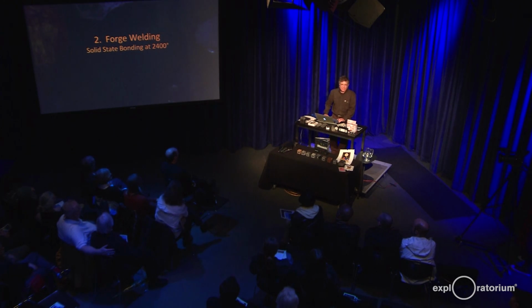So the second point that I'd like to go over is forge welding. This is an amazing process. It's my favorite thing to do in the forge. And what it is, is a solid state bonding of two pieces of iron at about 2,400 degrees.